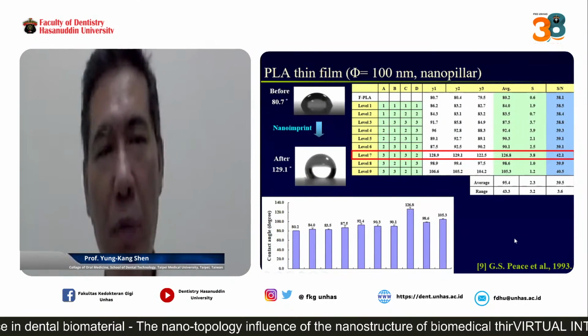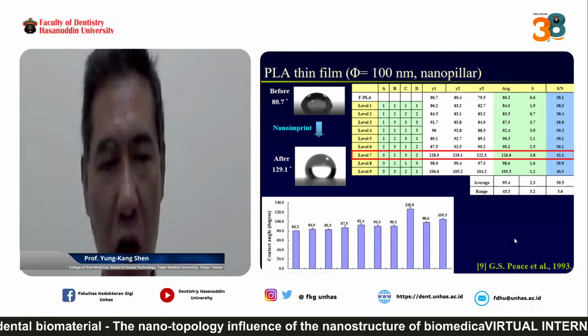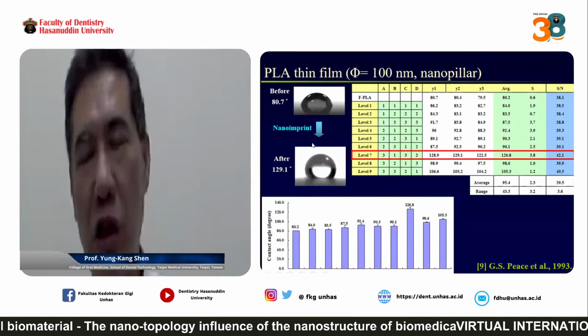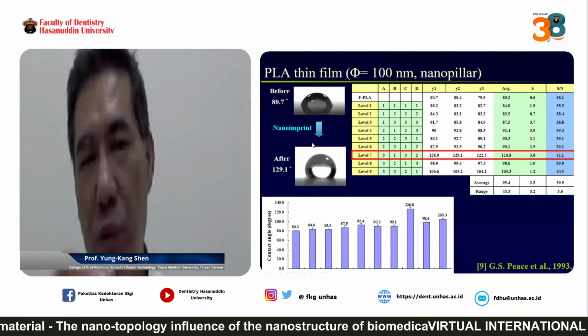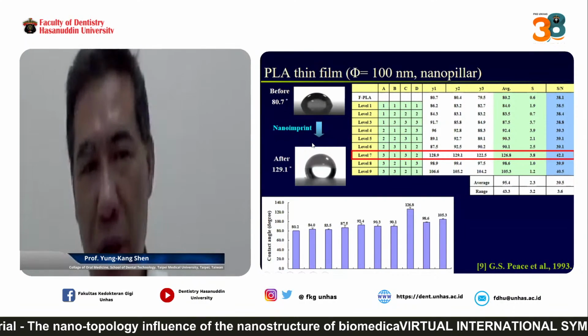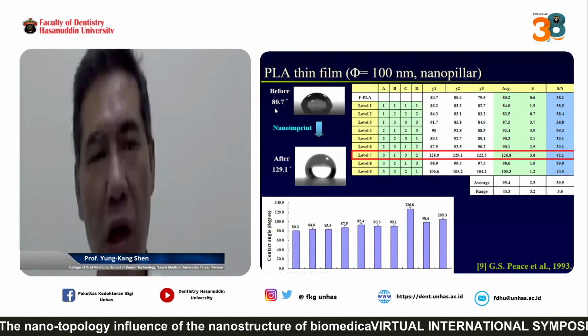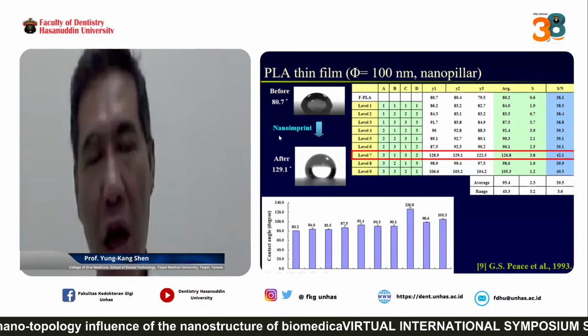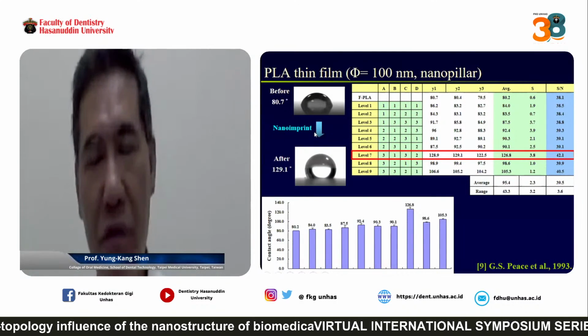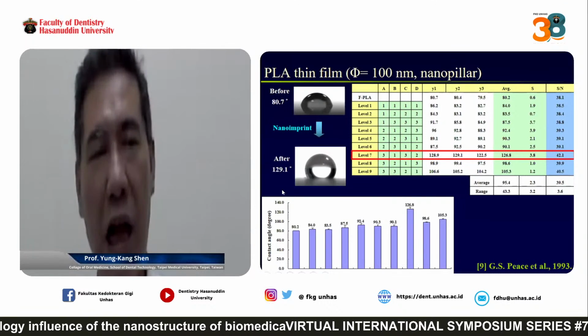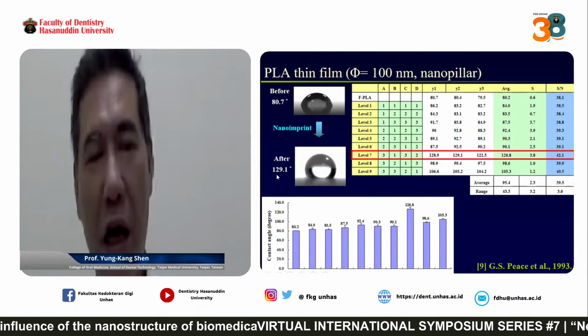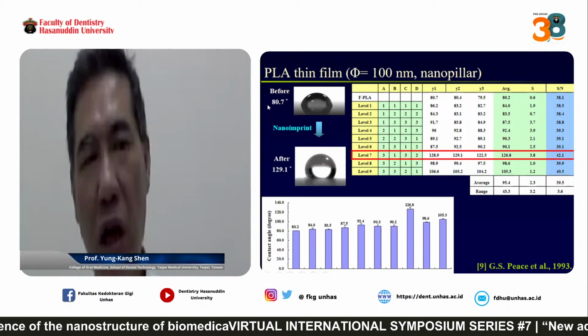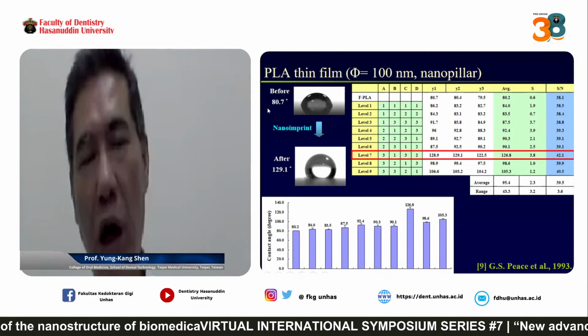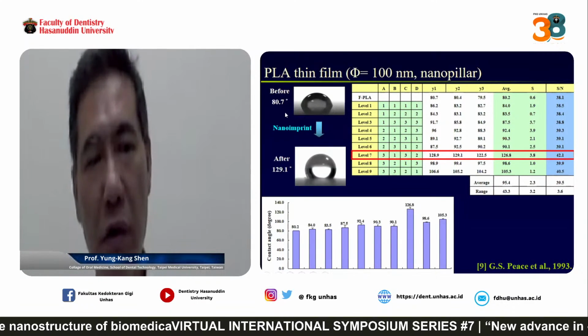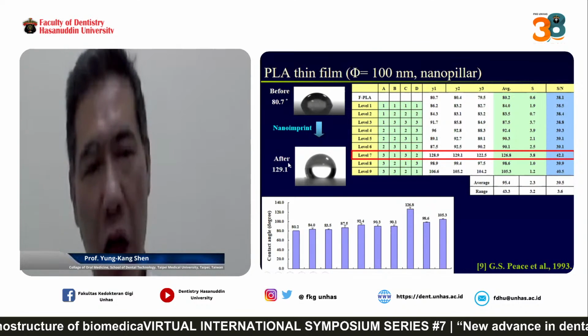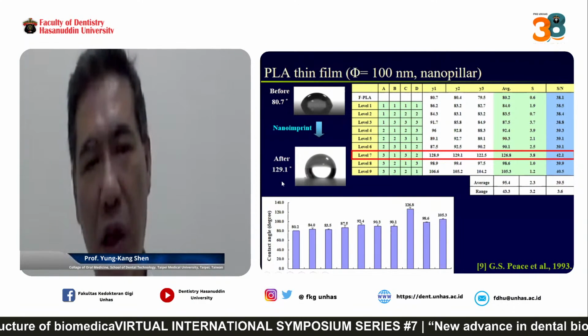First, I will talk about the PLA thin film with a diameter of 100 nanometers. If I use the contact angle meter to drop liquid on the pure PLA thin film, with no nanostructure, the original contact angle is 80.7 degrees. After nano imprint, the PLA thin film has nanostructures on its surface, and the contact angle changes to 129.1. So before nano imprint, the PLA is hydrophilic, and after nano imprint, we get hydrophobic properties.